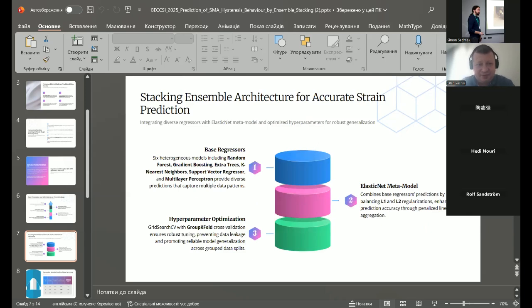The second part, ensemble models for accurate strain prediction, was as follows. It integrates diverse regressors with an elastic net meta model and optimized hyperparameters for robust generalization. We had base regressors, six heterogeneous models including random forest, gradient boosting, extra trees, k nearest neighbor, support vector regressor, and multi-layer perceptron. They provide versatile predictions that capture multiple data patterns.